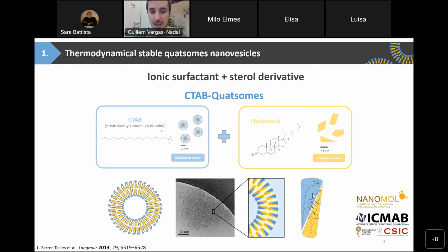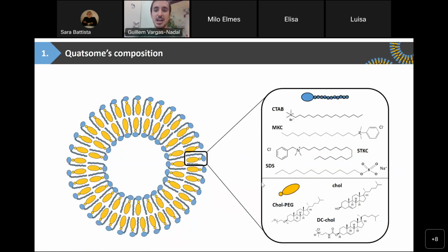However, when they are mixed together, they form this closed, spherical nanovesicle, which is called quatsomes. And here you can see how the cholesterol and the CTAB are structured in the bilayer. So they form this nanovesicle, in this case, these quatsomes. And quatsomes, as I told you, are composed of ionic surfactants and cholesterol. So depending on the surfactant and the sterol derivative that we use, for example, cholesterol modified with some targeting unit or PEG molecules, we will have different properties depending on the molecules that compose them.